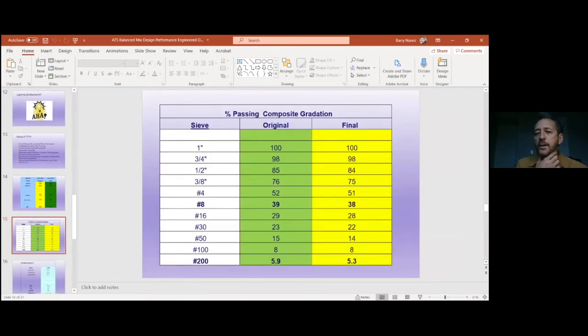So here's my final gradation. You can see that there's not a lot of change. 98 on the 3/4, 85, 84 on the half, from 76 to 75 on the 3/8, 52 to 51 on the 4. The 8 screen only changed 1%, 39 to 38, 29 to 28, 23 to 22, 15 to 14, 8 and 8 on the 100. The point that we did in between was at a 5.6. That was our first attempt.